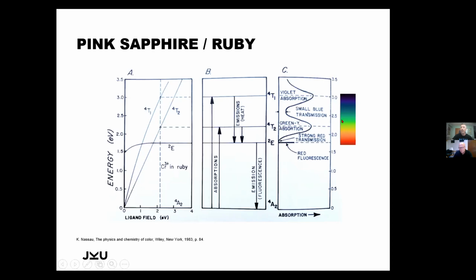What remains is the transmission here in the blue and in the red. And if you look closely, you see that the transmission in the red goes to 0 energy. So red is completely transmitted, and the blue does not go completely to 0, but we have sort of a lighter blue shade. So this is why a ruby generally has a red and a bluish red color.